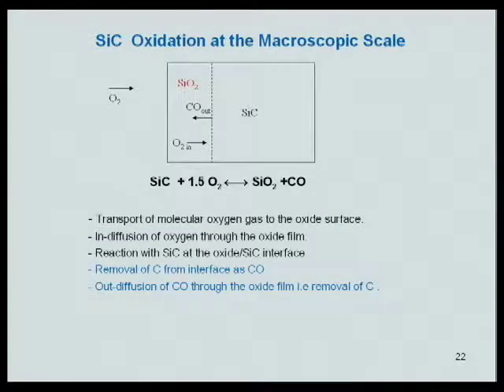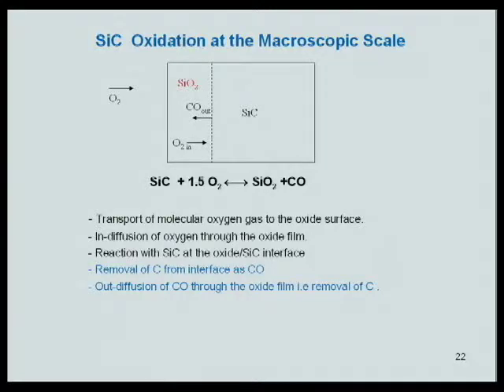So what's going on? Why is the mobility so degraded when we have current flow at that interface? One difference is that when silicon dioxide is formed by reacting silicon and oxygen, the reactants, silicon and oxygen, are the only thing that is around when the oxide is formed. In the case of silicon carbide, we have carbon. And when the chemical reaction occurs, there's excess carbon that's released. It forms carbon monoxide, and the carbon monoxide gas diffuses out away from the interface, out into the outside world.